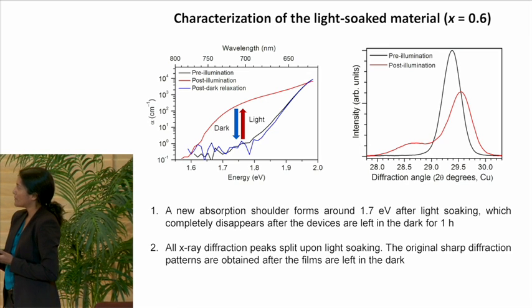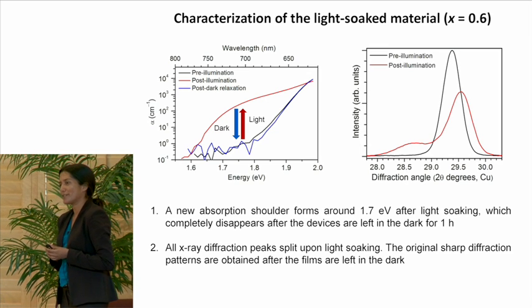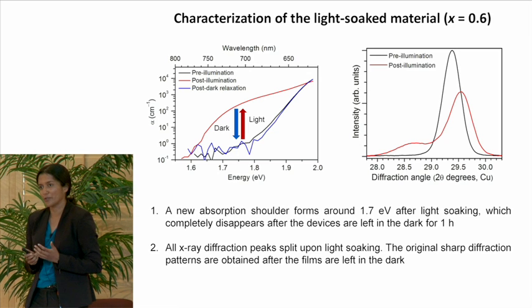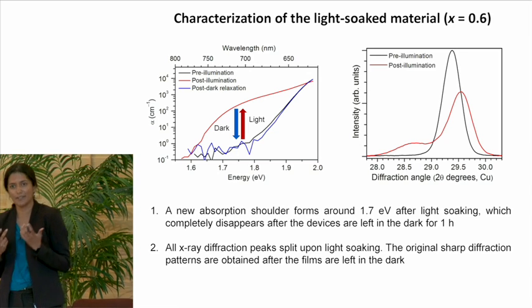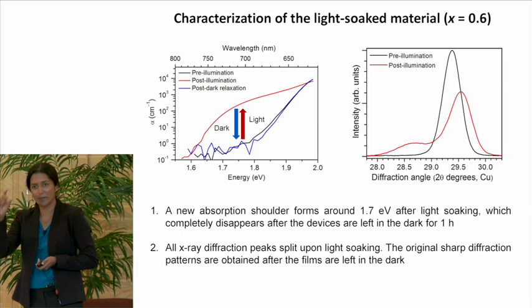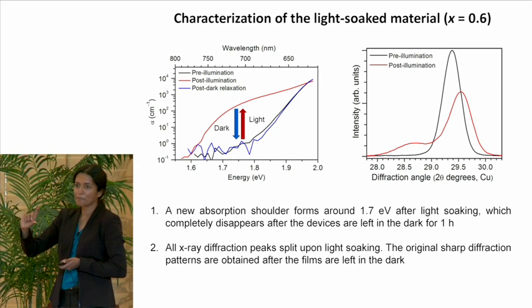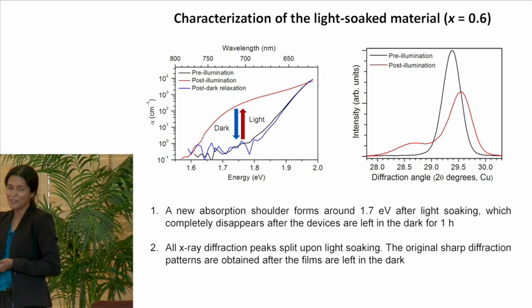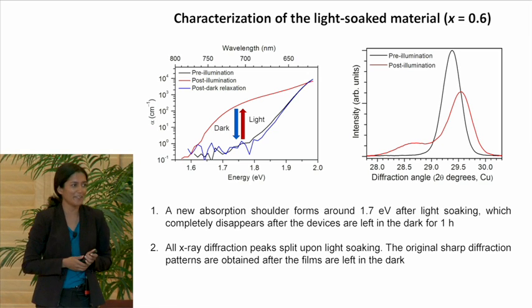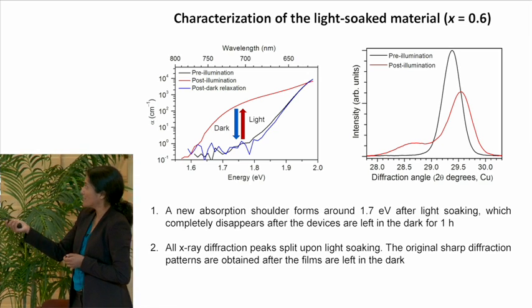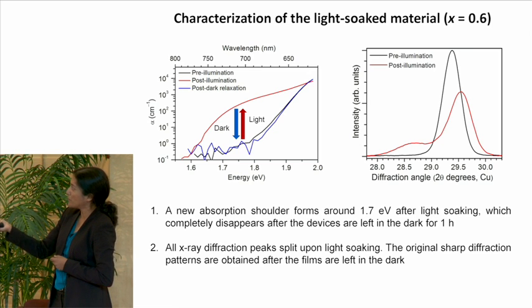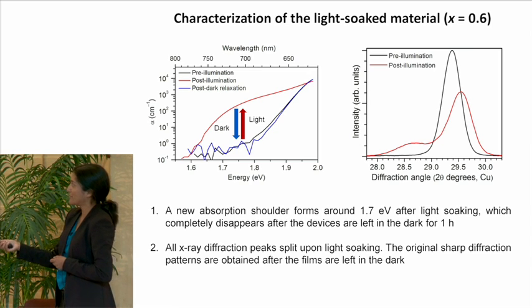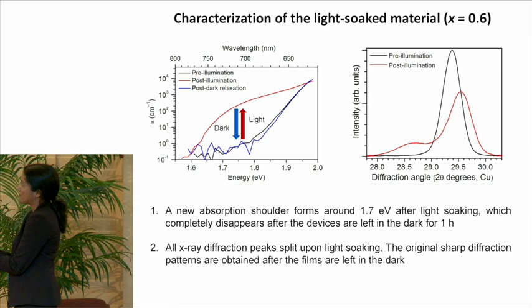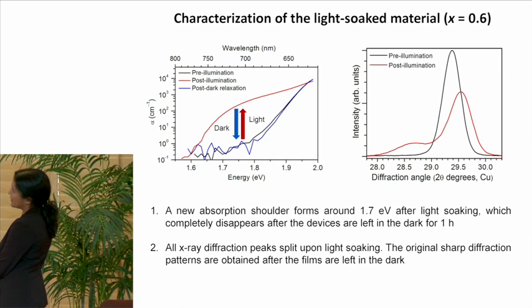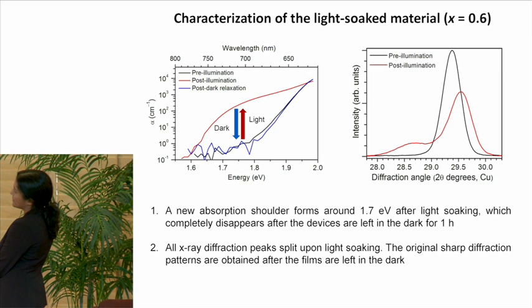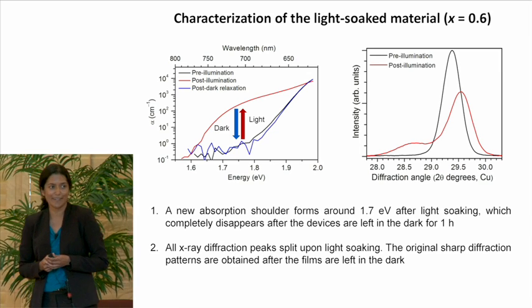So he decided to look at the X-ray powder diffraction pattern of these materials under illumination. So he employed this very sophisticated experimental setup where he suspended a bicycle lamp inside the diffractometer. And he just turned on this lamp, and this was enough to cause a change in the powder pattern of this material. When the light is turned on, he sees that every peak is split into 2 peaks. And when the light is turned off, he sees that the original peak grow back in. And these split peaks show the presence of a material with a larger lattice than the original, as well as a material with a smaller lattice than the original mixed halide perovskite.